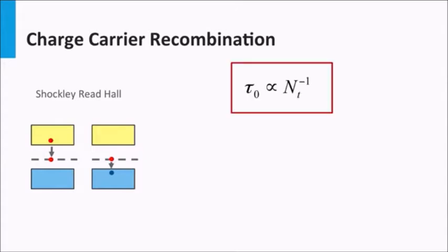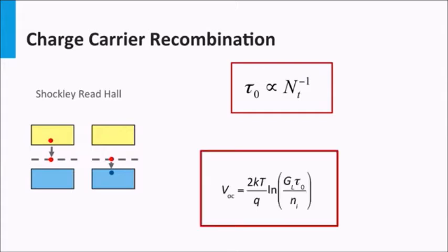The origin of this mechanism is the trapping of the mobile electron at defects that have an energy state in the bandgap. The electron is trapped until a mobile hole finds the electron, after which both charge carriers recombine. Shockley-Read-Hall recombination depends logically on the defect density. In the simplest approximation, the minority charge carrier lifetime is reciprocally dependent on the defect density Nt. This means the larger the defect density, the shorter the lifetime, and the smaller the open circuit voltage. The defect density limits the extent to which the quasi-Fermi levels can be split.